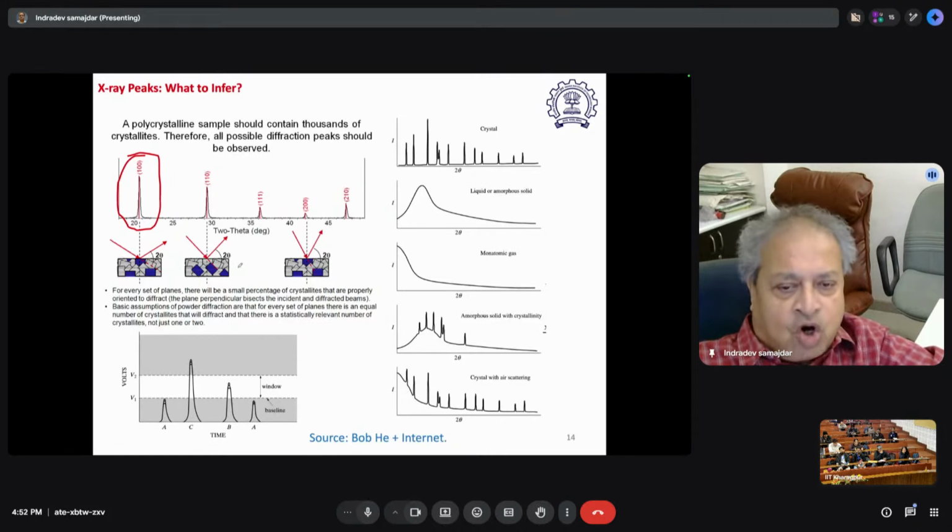So a lot of people change targets. I know folks who do that on a routine basis. I'm talking about so-called big multinational companies. Foolish. Because when you change the target, your optics, which is all important, is geared up for one target. It doesn't change. The coatings on your mirrors and lenses do not change.